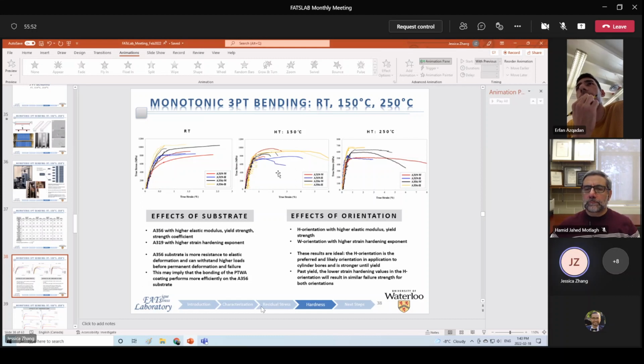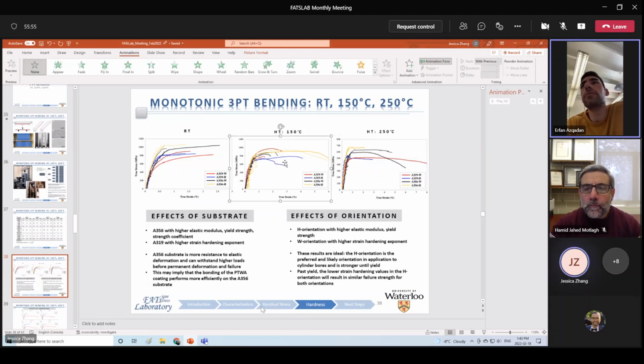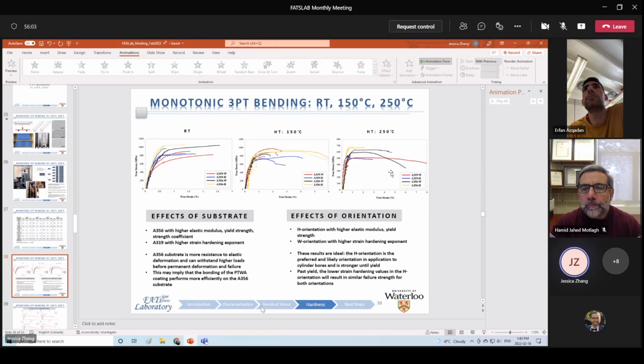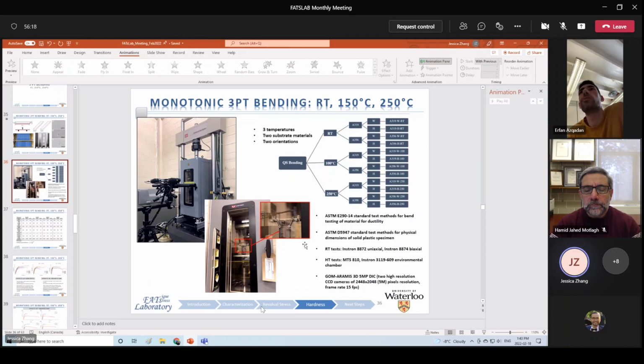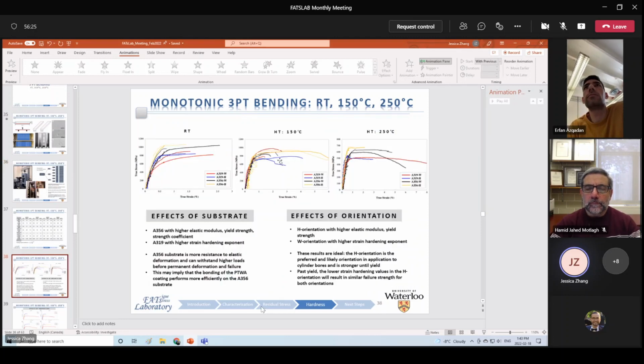We actually did see in some properties that the trends at 150 didn't really follow successively from room temperature to 150 to 250, but we are not quite sure yet why. We are also taking a look at the differences between the testing. As you see, we had to use different test machines: unfortunately, for room temperature we used the 2 Instrons, and then for the higher temperatures we used the MTS for these 2. So you've noticed that the 150 doesn't quite fall in place between the room temperature and the 250. Yeah, that's correct.